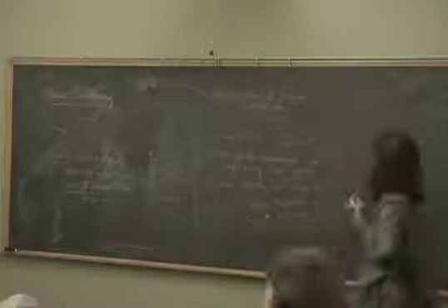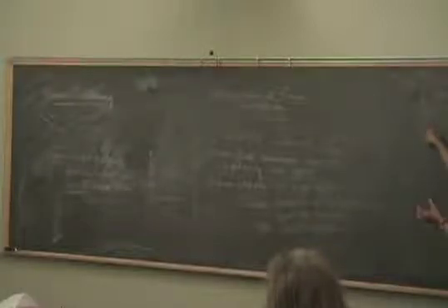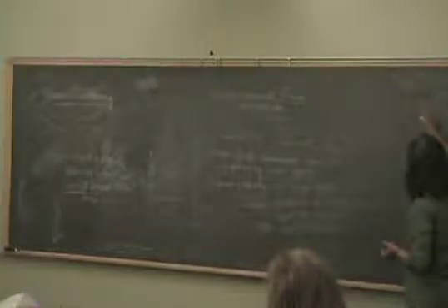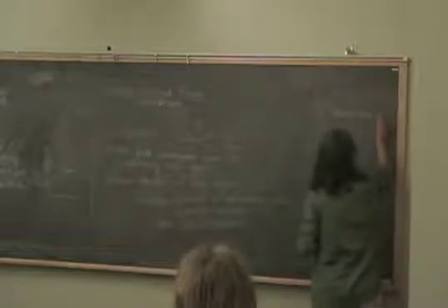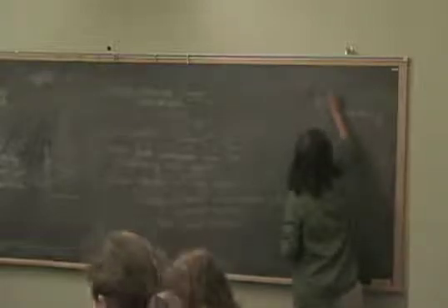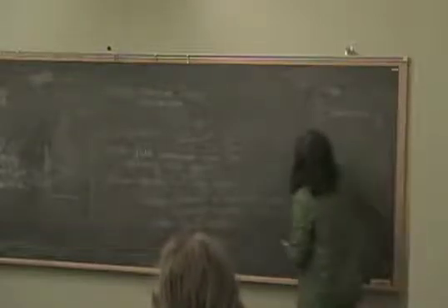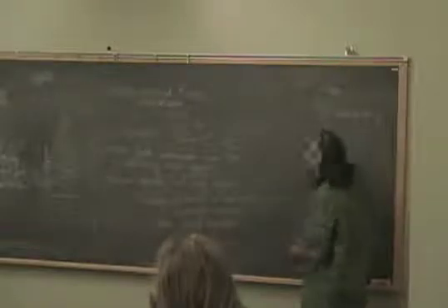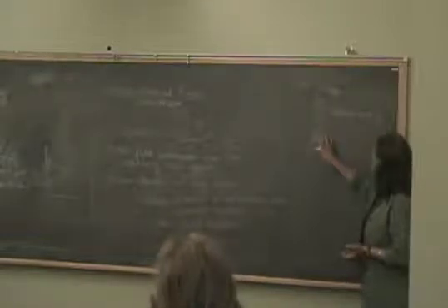I don't know all the details, but here's the point: if you shine a laser on this metal sphere or metal dot at a frequency which is resonant with the dot, then you excite the dot at the resonant frequency of the plasma oscillation. So this one has plasma oscillations, the surface plasma frequency. So the laser excites the metal sphere at that frequency, and its electric field is now greatly concentrated. My electric field arrows are now very concentrated here, and this is now coupling to some molecule. So that's the idea, that the signal is enhanced.